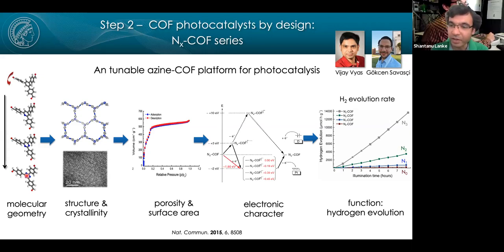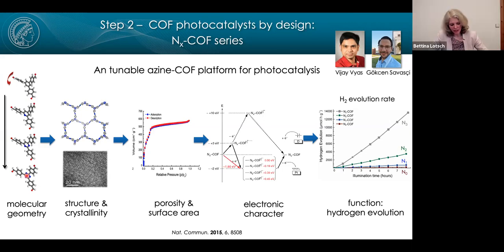Okay, and what was the quantum efficiency of the COF materials? It varies a lot. For example, the NX COFs that you see here have very low quantum efficiencies, so low that we don't really dare to quantify them. They are not very emissive, not at all. But it depends on the system. Of course, other systems can be very different.